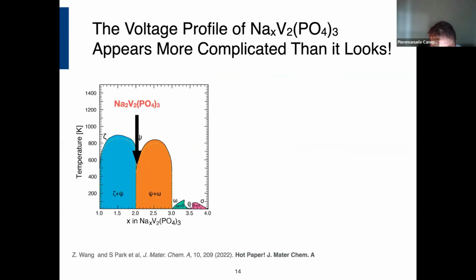If you look at the phase diagram, this is the predicted phase diagram from our group. We use, of course, density functional theory, cluster expansion, and Monte Carlo. We have expertise in this area. It appears much more complicated than our experimental colleagues thought, and this has driven the next experimental step. This is a success story where theory has been applied to understand this material in detail, and some revelations come out of the theoretical calculation that are then implemented into understanding experimental aspects. In this phase diagram, the composition axis tells you how much sodium you have, and on the y-axis we have temperature.